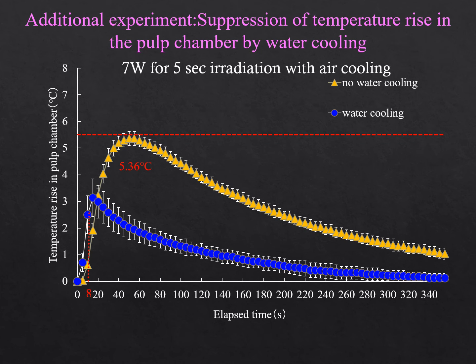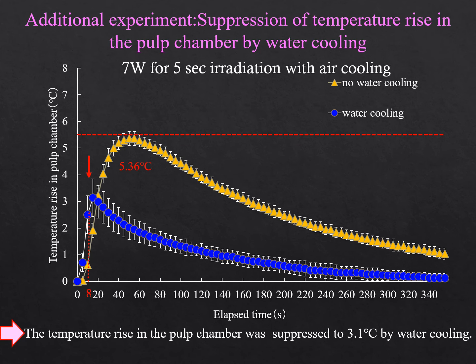As an additional experiment, 7 watts for 5 seconds laser irradiation raises the pulp chamber temperature to near the degeneration temperature, thus risking pulp damage. Therefore, when the bracket base temperature reached 80 degrees by laser irradiation, 8 seconds after irradiation, cold water was dripped onto the bracket, and then the temperature rise in the pulp chamber was significantly suppressed to 3.1 degrees. The water cooling method is a safer method for protecting the pulp.